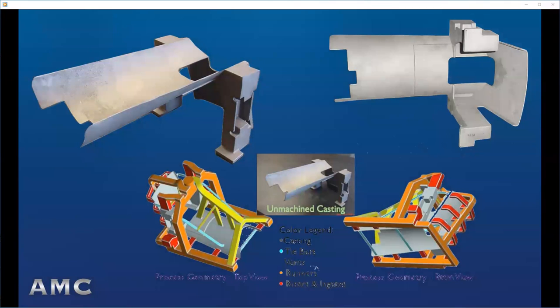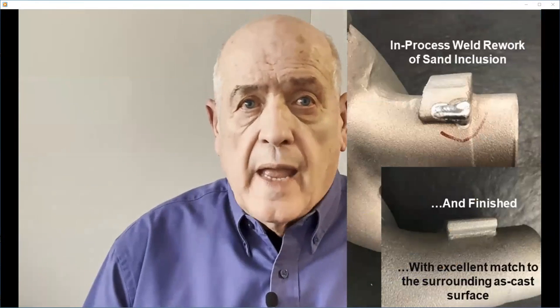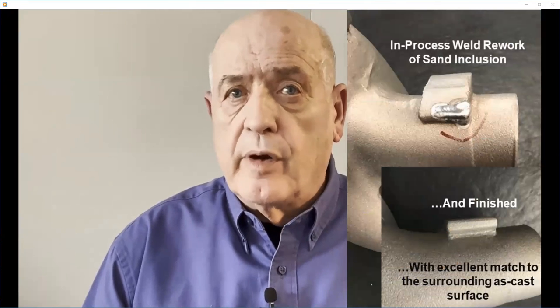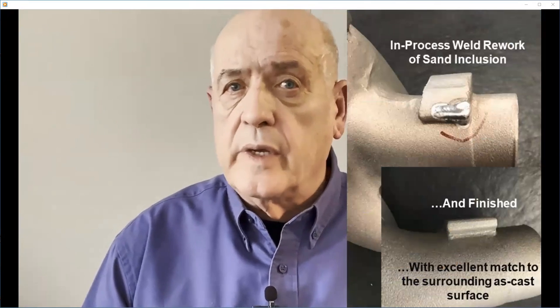What is our purpose is to address reality for high specification, complex geometry castings, specifically DLA legacy castings. That reality is that finishing of these process interface geometry markers has to be essentially perfect within the specified as-cast dimensional tolerance profiles and surface finish. It's a lot of work and tender loving care to make these markers essentially perfect within specification, but first article inspectors will not realize the reason for their presence and will not have the original engineering authority available to say, oh yes, those markers need to be there, those are okay in those positions. Well, back in the day, with the original design authority and the original supply chain, those informal deviations actually happened. Now, in a cold start, it won't happen.